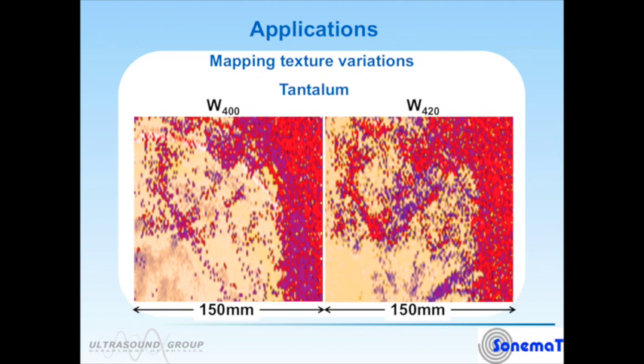We've got two of the three parameters that we need to define texture, and quite often it's just as important to know if there's any inhomogeneity. So the 400 and the 420 subscripts on these W parameters, they're effectively a kind of quantitative measurement of a particular parameter that tells you how grains are aligned in this material. In this case, we were just interested in, was the plate homogeneous? And we can see clearly here that the plate is not homogeneous.